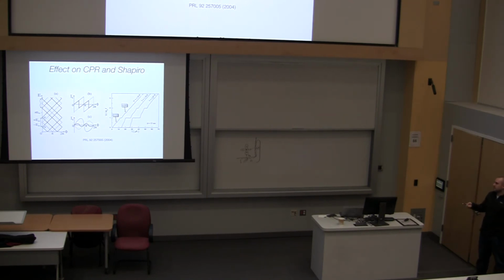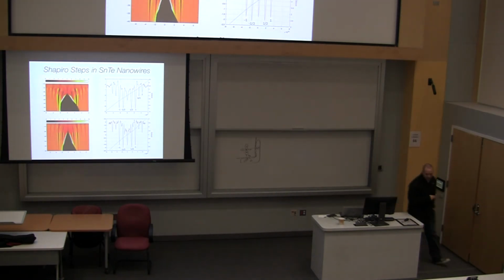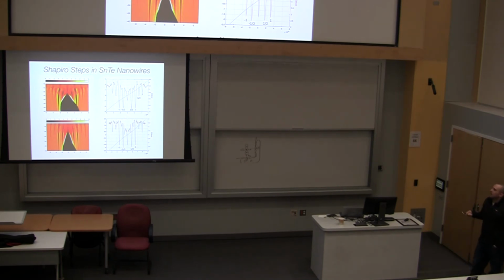And so what happens is that when you're in the right regime, such that you have a 0 pi junction from this material, in addition to steps at the primary values that you expect for Shapiro, you start to see these half steps begin to form. And when we do these measurements on our nanowires, we do in fact see very predominant half steps. And in some cases, the half steps are even more prominent than the fundamental steps. And this is not what you would expect if you just had a skewed current phase relationship.